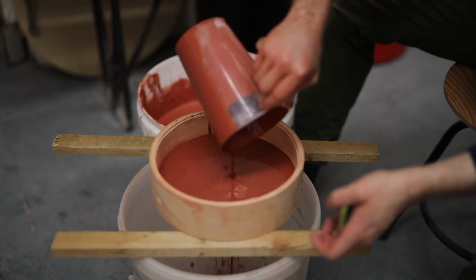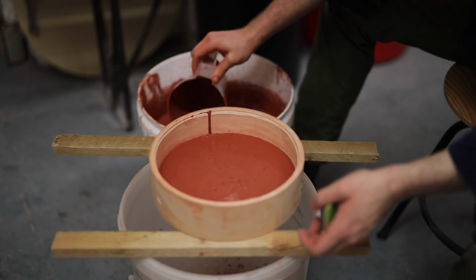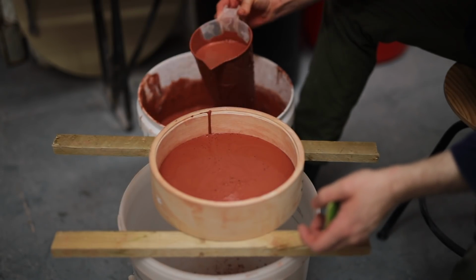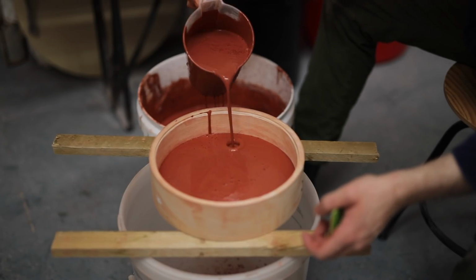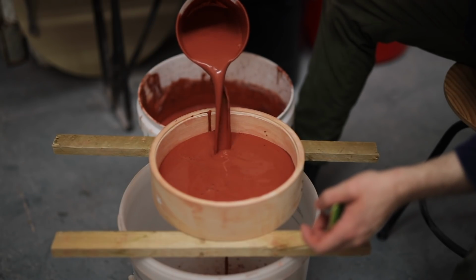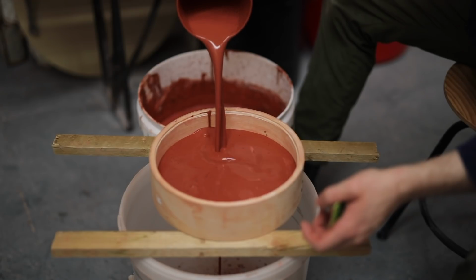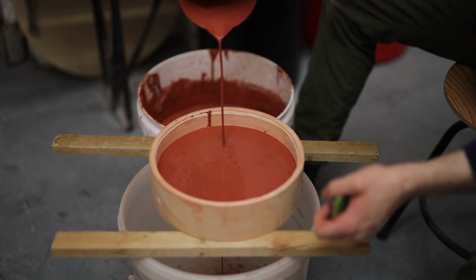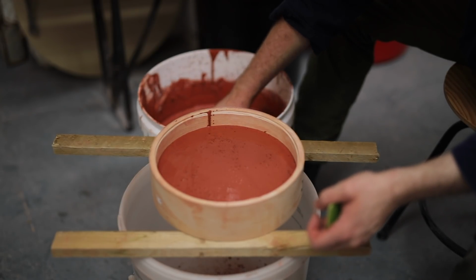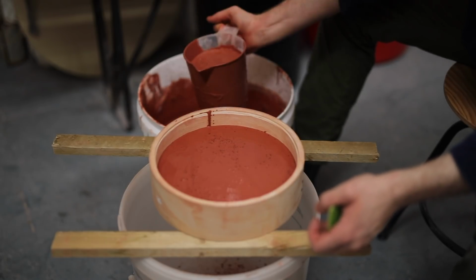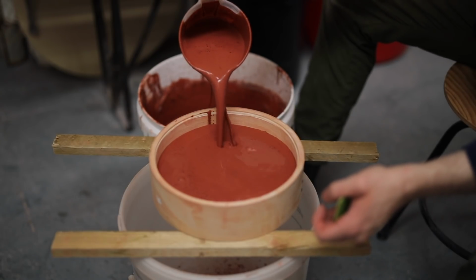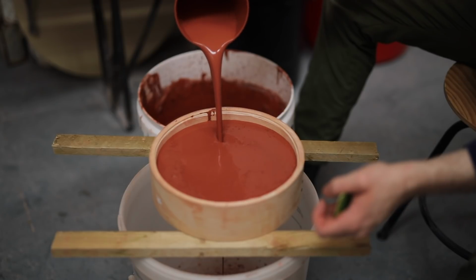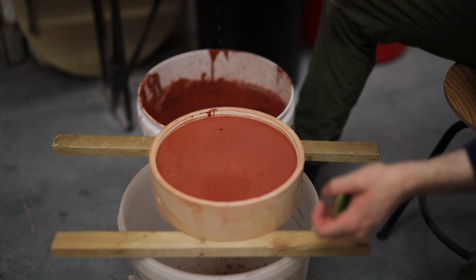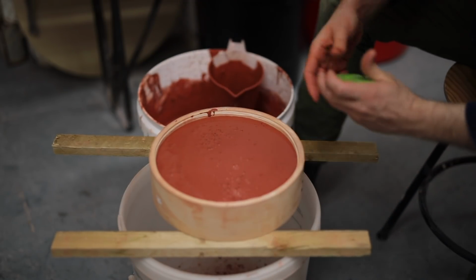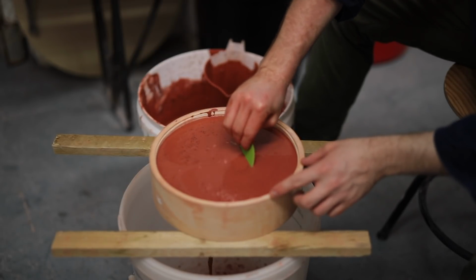So in this instance, I'm using a feldspathic crackle glaze with red iron oxide acting as the colorant. If this particular mix was fired in an electric kiln that contains ample oxygen, you would end up with a sort of putrid yellow colour. But if you take this same glaze recipe and fire it in a reduction atmosphere in a gas kiln, like I have, you end up with lots of pleasant green hues which have lots of depth and iron speckling due to the reduction process.